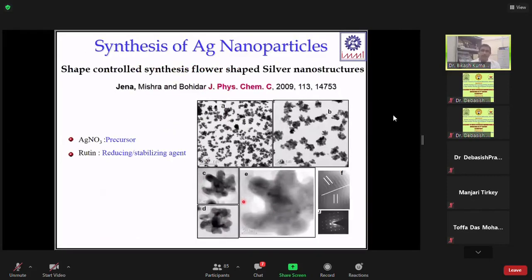Also, we have synthesized some silver nanoparticles. You can see dendrite and flower shaped nanoparticles synthesized, using rutin as a reducing agent. This is a simple biomolecule. You just add it to the precursor and stir for a few minutes and you can observe these nanoparticles form. And these nanoparticles have very good antibacterial property that we studied. We compared to the spherical counterpart, and these different shaped silver nanoparticles show better antibacterial property because their interaction with the bacterial surface is greater, so they can kill more bacteria than the spherical ones. We observed this and it is published in JPCC.